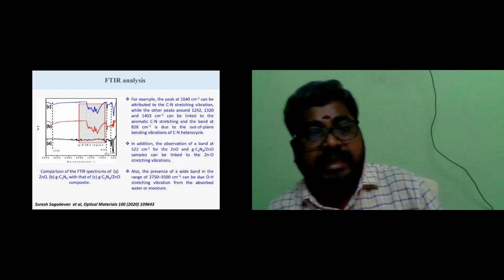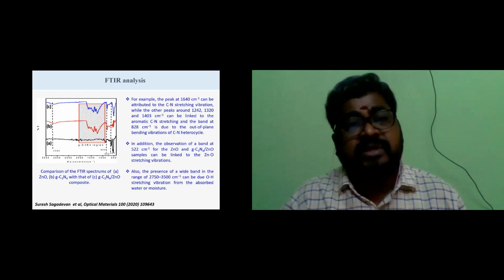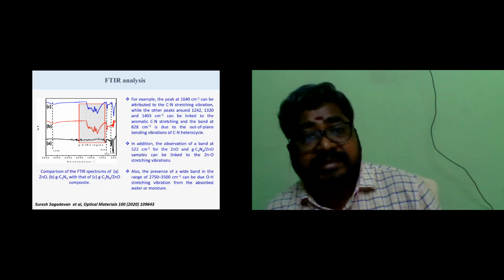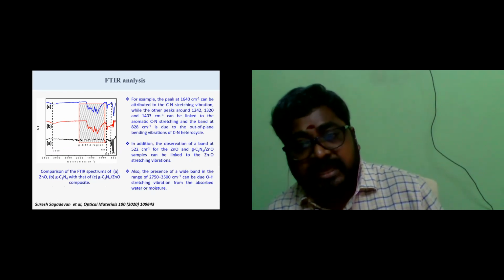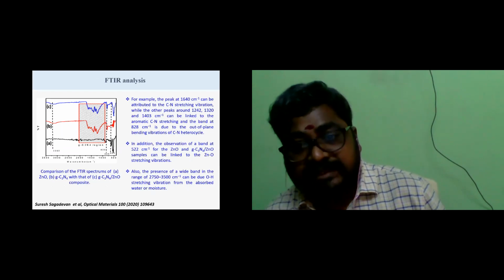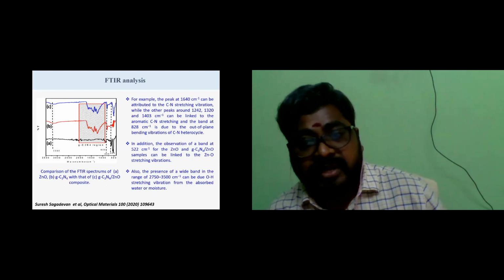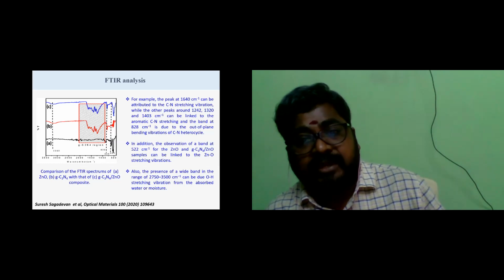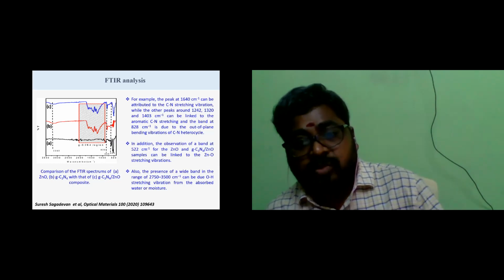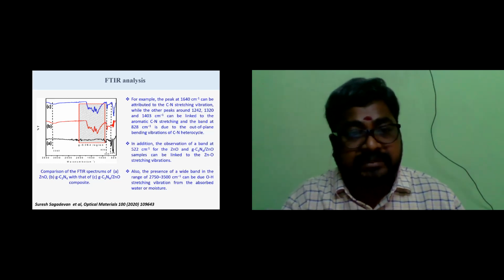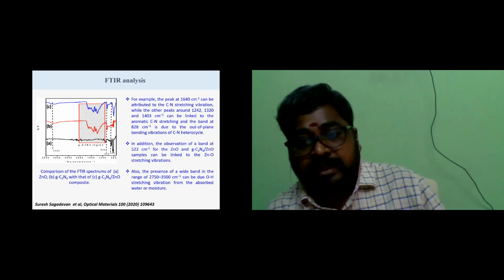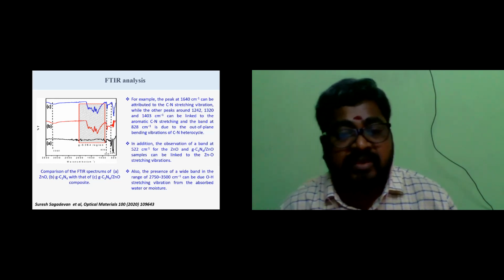And the band at 628 centimeter inverse is due to the out-of-plane mode. So the CN stretching also clearly states that the graphitic carbon nitride is present in this composite. And we could also confirm the zinc oxide bonding, zinc with oxygen bonding, which occurred at 522 centimeter inverse. Also, the presence of a wide band, you can see here, indicates the OH stretching vibration from absorbed water or moisture.